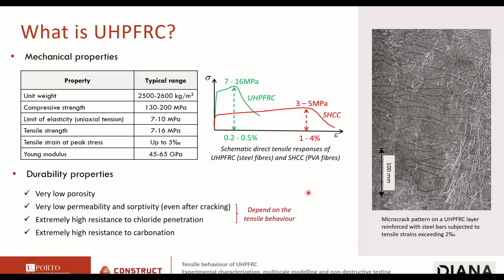Yeah, so it has a high limit of elasticity. So the stress at first cracking can vary according to the composition, but typically between 7 and 10 megapascals. And depending on the fiber content, we can have post-cracking tensile strengths that can go up to 16. You can see larger values, these are the most typical ones. So besides this, one important thing is that with the proper fiber content and orientation, as we will see, the material can be strain hardening in tension, as you see here in the green curve.